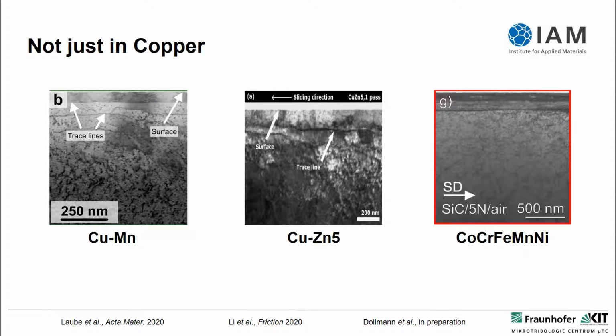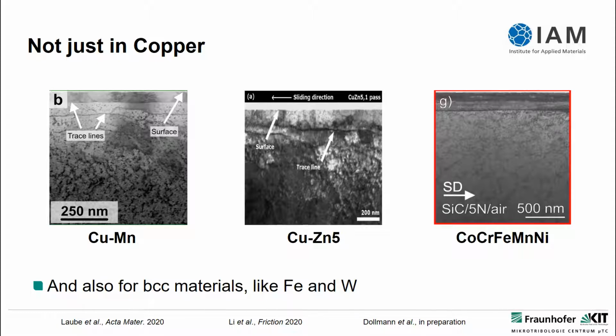We have also looked at BCC materials like iron or tungsten, and also there we do see this dislocation trace line phenomenon. So it seems to be really a mechanism that you can find, at least in a certain range of stacking fault energies, in other materials, not just in copper.